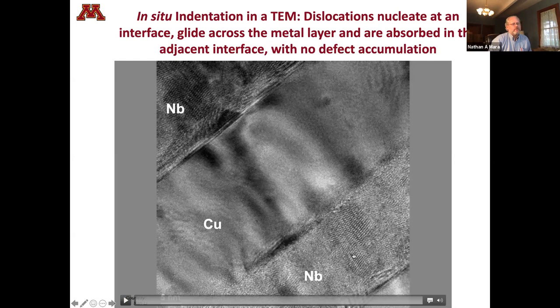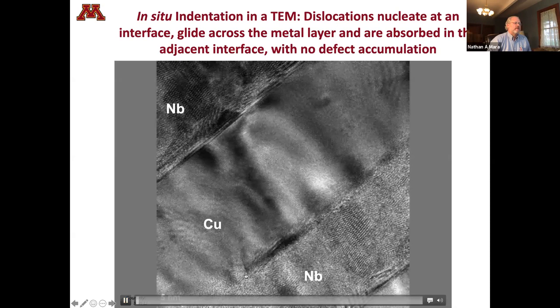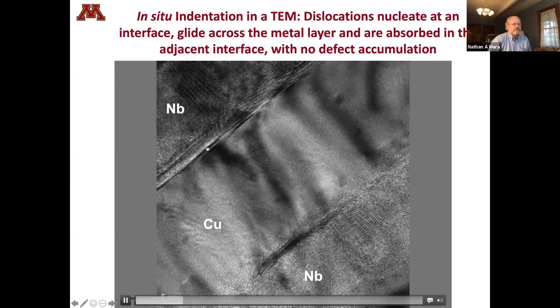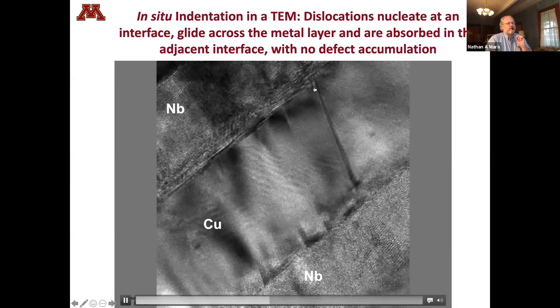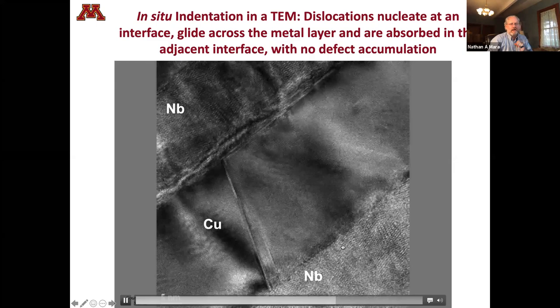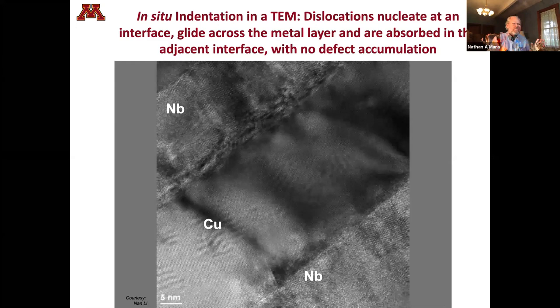And what you're gonna see are dislocations that nucleate at one interface, travel across the layer, disappear in the opposing interface. And so this is what I'm talking about when we talk about interface dominance, is that these dislocations are born and they die in the interface. So that structure of that interface is what dictates exactly how this material deforms.